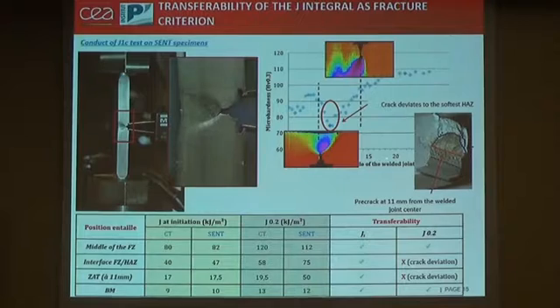In contrast, with a crack in the interface or in the heat affected zone, we have a deviation and the cracking goes to the softest, weakest, heat affected zone, which can potentially be the detrimental point of the welded joints. So the transferability of G at 200 micrometers will not be achieved in all cases, but at initiation, the transferability was achieved for all the tests.